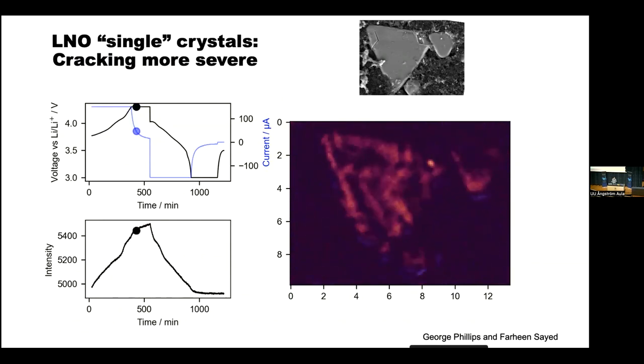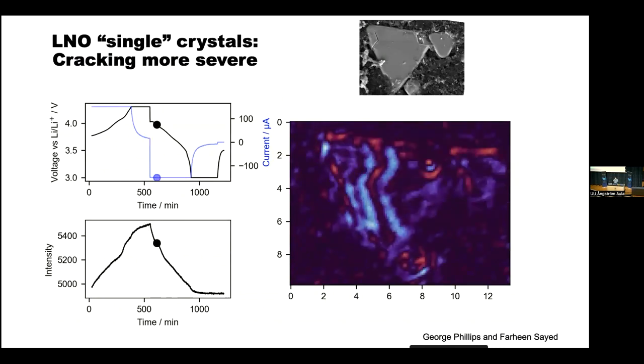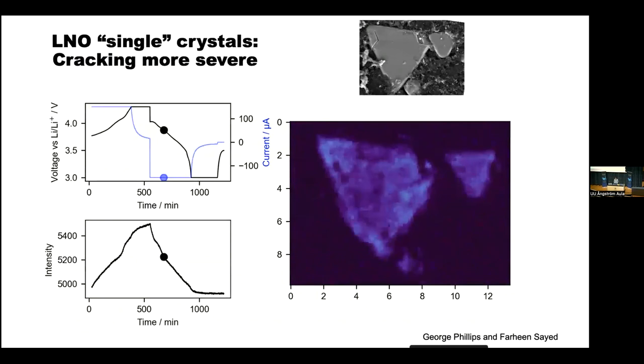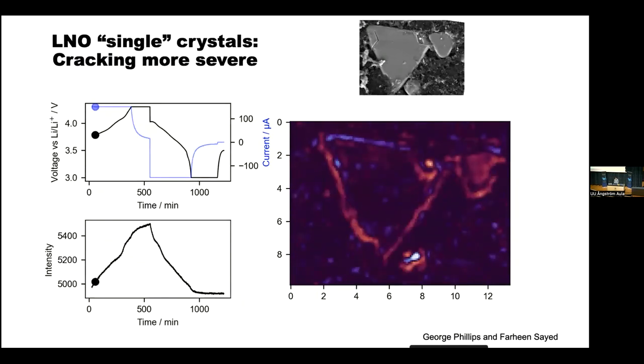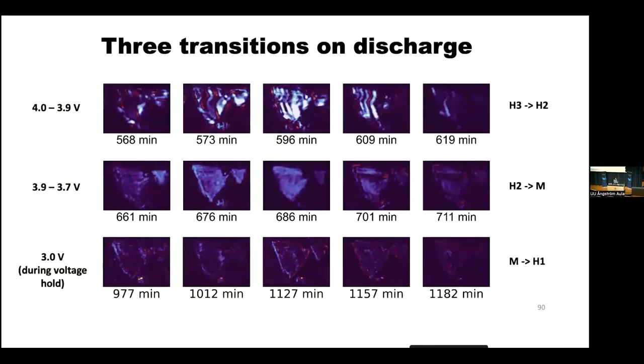It's not behaving as a perfect single crystal. In fact, there's some really weird stuff in the H2 to H3 transition, where you've got a very large change in the cell parameters. You can see this more clearly in the discharge at the top. So this is the H3 to H2 transition. There's a whole series of zigzag in the structures.